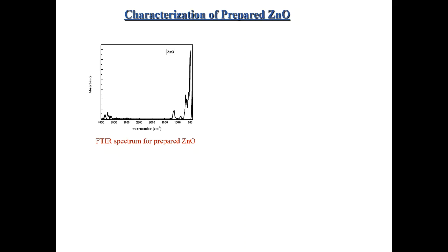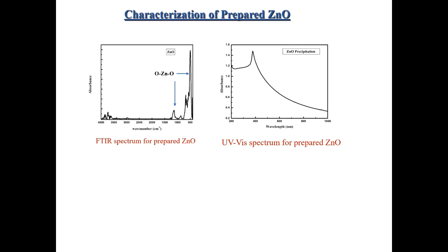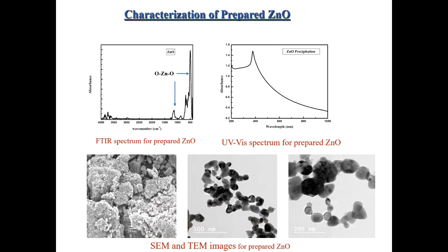FTIR of zinc oxide showed a band that characterized and confirmed the formation of zinc oxide at the nanoscale. Also, the UV-visible spectrum of the zinc oxide nanoparticles showed a peak at 376 nanometers. Then the prepared zinc oxide was also analyzed by scanning electron microscope and transmission electron microscope to study its morphology, which indicates that the particles are mainly spherical in form and aggregate into larger particles, with particle size from 20 to 50 nanometers.